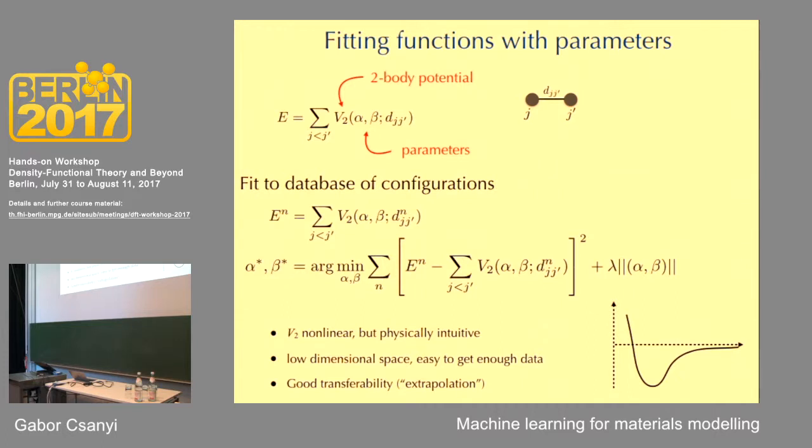Right? So a typical material will have distances between 1 angstrom and, say, your cutoff is 6 because the interaction goes to 0 there, and everything between 1 and 6 you can sample, no problem. The problem is accuracy, that this function just doesn't have the capability of matching the real thing, but it's not a problem of extrapolation. This will change when we go to machine learning. It'll just go the other way around. We can represent any function with machine learning, but in a high-dimensional space, we will have the problem of extrapolation.